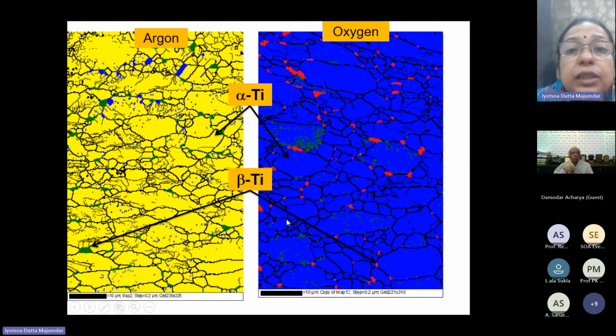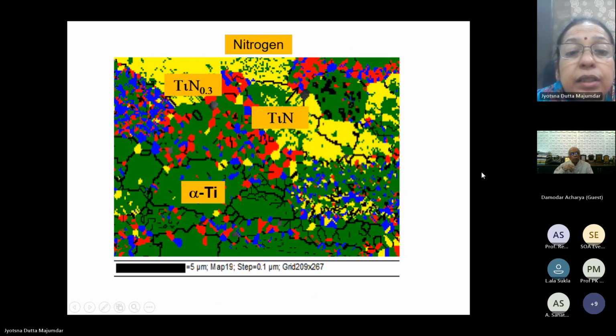So here again, in the argon and oxygen environment, we see a lot of beta phase, mostly alpha, and some oxides are also there. Red particles are very small oxides which are present on the surface. In nitrogen environment there are a lot of nitrides, and alpha phase are also there.